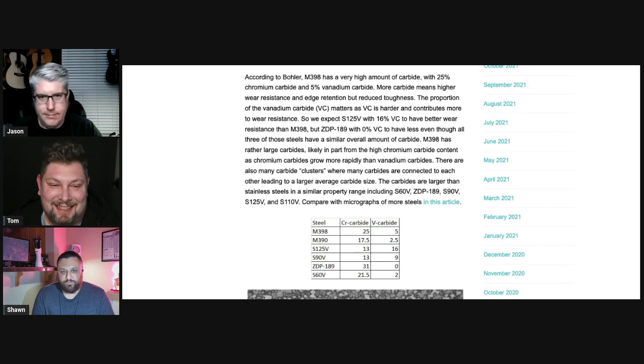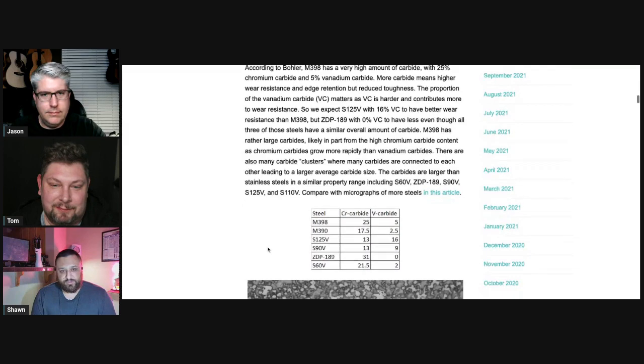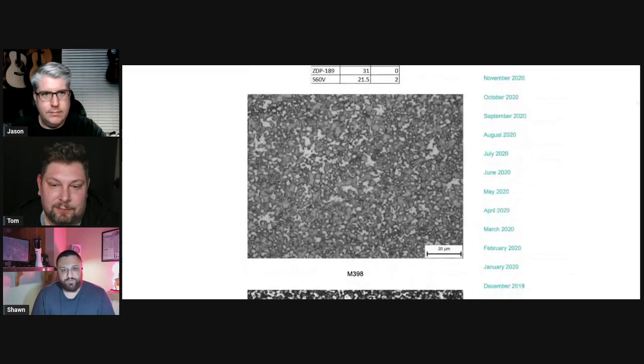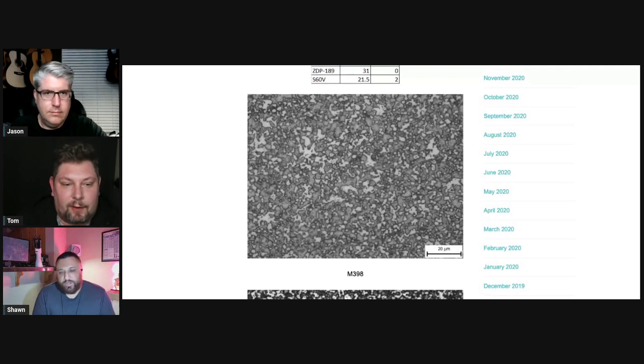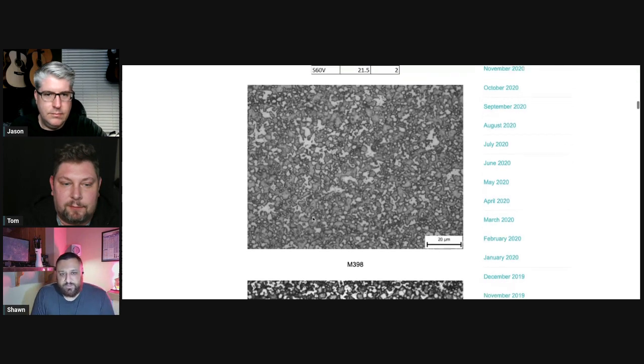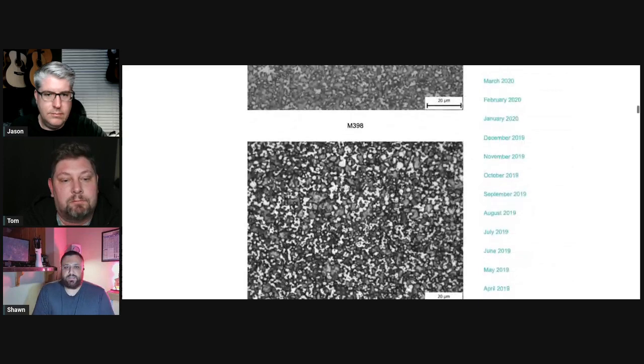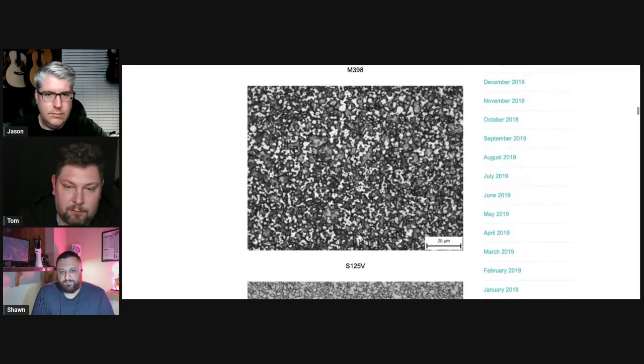And these aren't just like regular chromium carbides. They're basically vanadium doped. So they're a little bit harder than your pure chromium carbide. And we'd also have about 5-6% of the vanadium carbide hanging out. That's a very hard particle in there. But what I thought was neat about this material was the fact that we had mostly these vanadium-rich chromium carbides, which are going to be a little bit easier to sharpen technically than just having majority vanadium carbide.